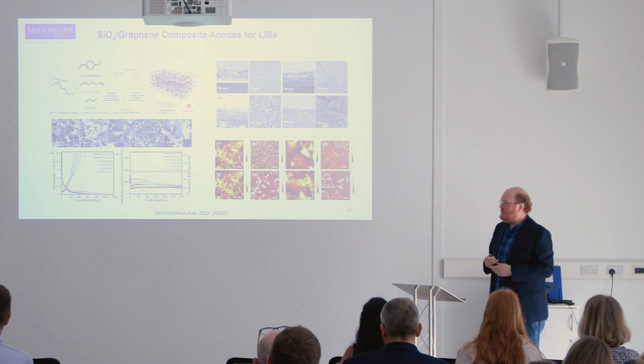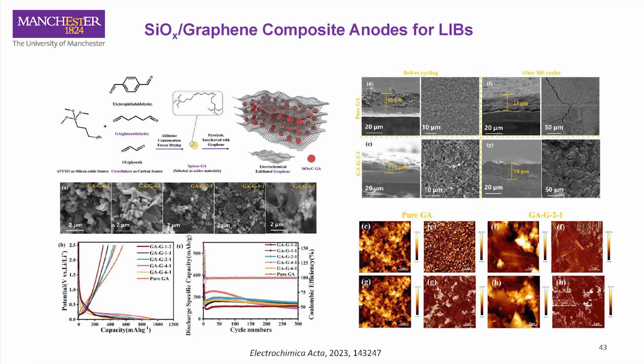Finally, in terms of batteries, graphene is already used a lot as a conductive additive in lithium-ion batteries. This can also be combined with silicon. Silicon is very interesting for batteries because it has such a high capacity. The problem with silicon is that obviously it's not very electrically conductive, and it also has a massive volume expansion. It can be over several hundred percent.